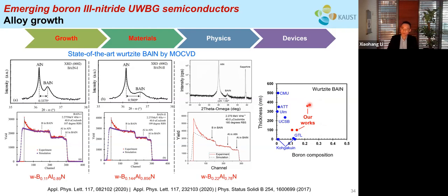So as you can see, we have the largest boron composition, and all of our samples here have thickness larger than 100 nanometers, which is sufficient for a majority of the applications. But in our group, we are still trying to push the composition higher and push the thickness higher as well.